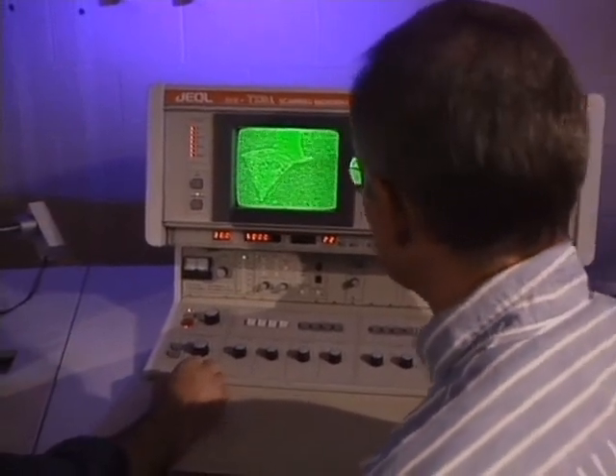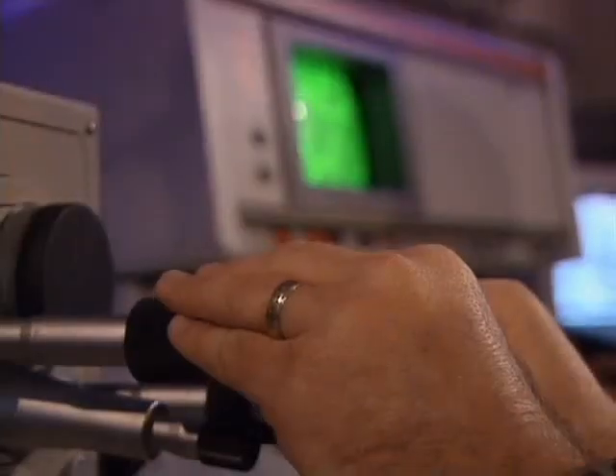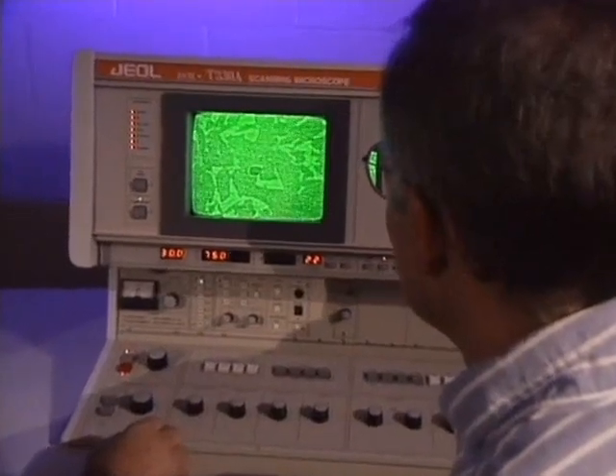Pearlite, lots of inclusions. Just focus it real fast. And then go back down in magnification, see what we have. They are looking for potential weaknesses and defects in the steel. Higher magnification shot. Lots of ferrite, pearlite, big inclusion. That's a big one, probably big old manganese sulfide. As they suspected, the steel is full of large manganese sulfide inclusions, chemical imperfections that create weak areas which cause the steel to be brittle.